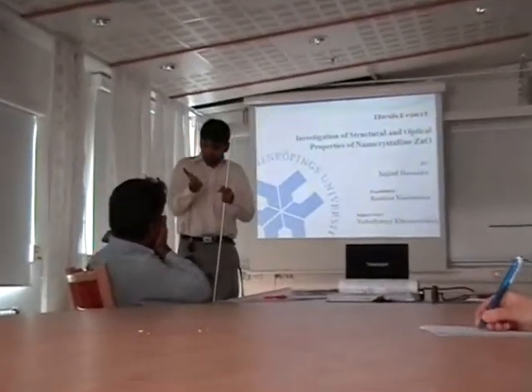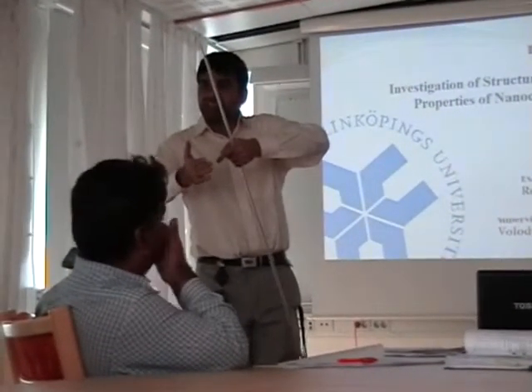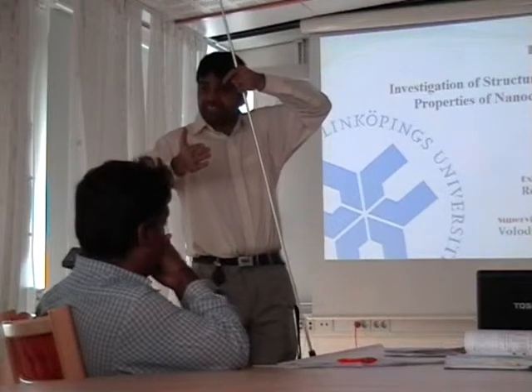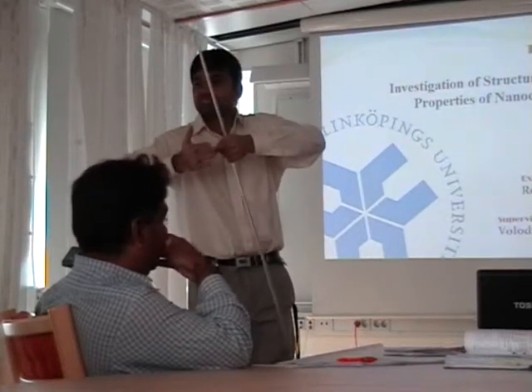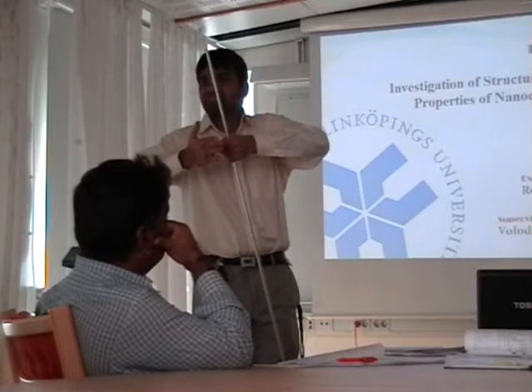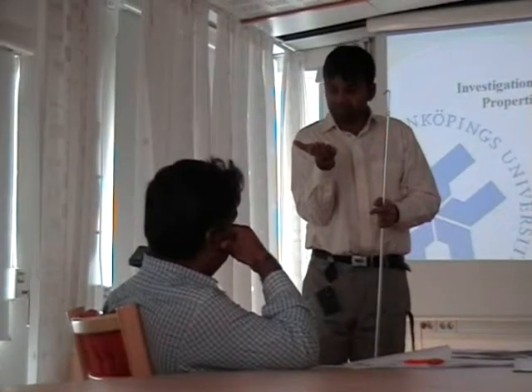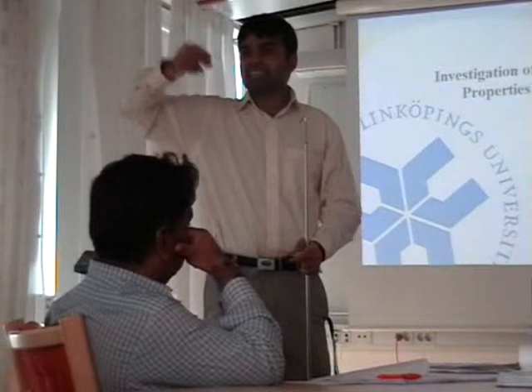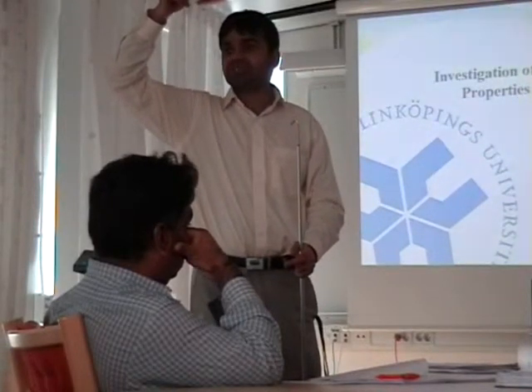Yeah, that's a very good question. Actually, in XRD, sample was placed perpendicular to the incident ray. The incident ray, they are directly put on the nanopillars. They are not on the film. And through PL, the sample was parallel to the laser beam. And they show a very intensive peak of near band edge emission. I still cannot tell. So you mean from nanopillar and X-ray diffraction? Actually, okay. Yeah. But maybe you can show the X-ray.